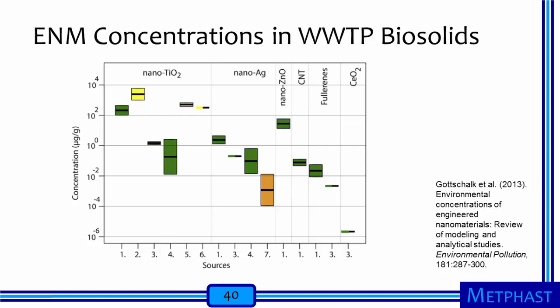A similar pattern among the various engineered nanomaterials can be observed for concentrations in wastewater treatment plant biosolids. Nanotitanium dioxide concentrations are generally higher than the concentrations for the other nanomaterials. In one study, concentrations of nanotitanium dioxide were measured to be larger than 1 milligram per gram of biosolid. Other measurements and estimates were lower for titanium dioxide, but concentrations were still greater than 100 micrograms per gram in